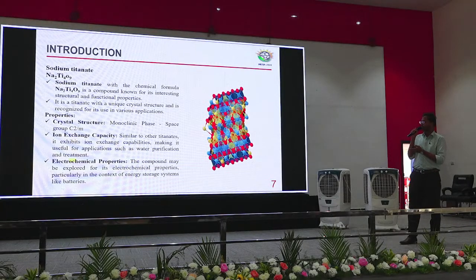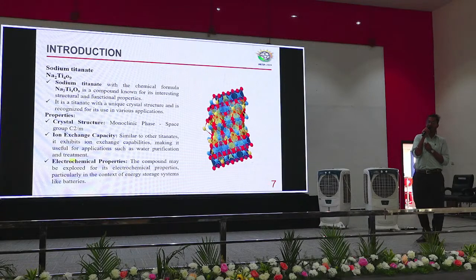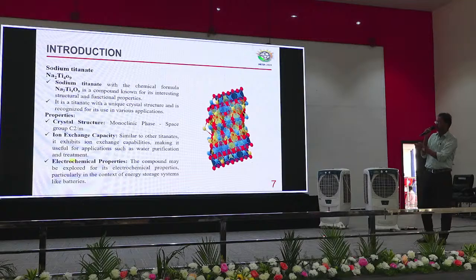This is my material. First we synthesized this material as titanium oxide. After that we planned to incorporate sodium, lithium and potassium. My work started with potassium, and next we moved on to sodium. This sodium gives comparatively good capacitance compared to the potassium studies, so we chose sodium. Here the red dots are the arrangement of sodium, and inside, the blue dots are the titanium. They are aligned between the two in a sheet-like morphology, while allowing penetration of ions into the depth of the molecule.